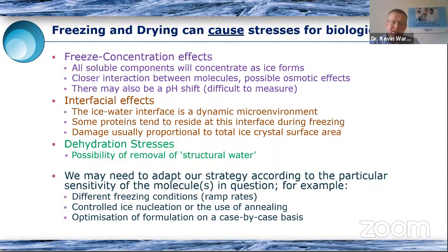On the other hand, we see that some proteins are susceptible to what we call interfacial effects. So they may not be destabilized by freeze concentration, but they might reside at the ice-water interface. And we know that's a dynamic microenvironment. And we know that if proteins are damaged at that interface, then the damage tends to be proportional to the surface area. And so again, that might direct us to change our freeze-drying conditions and maybe use slower cooling. Again, maybe we need to reconsider the formulation in that case.